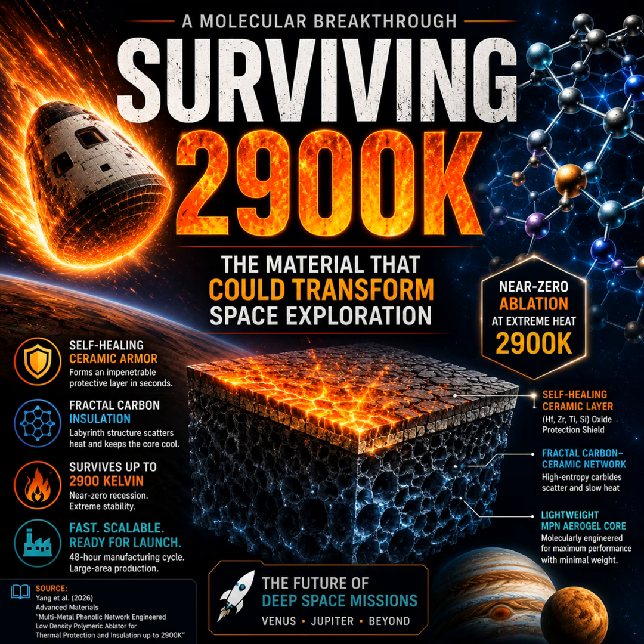And third, the interior evolution into that mass fractal geometry. It provides unprecedented thermal insulation by kinetically trapping the phonons at the nanoscale. It maintains a low backside temperature even after 25 minutes of 2900 Kelvin exposure. It's just a brilliant piece of material science. It really makes you think differently about the physics of heat.